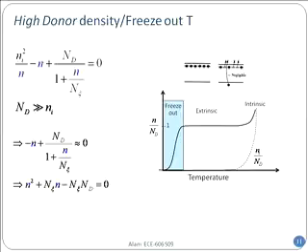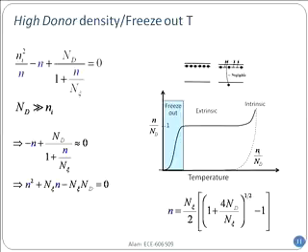And once you solve for it, you'll get an expression like this, which goes with N sub xi and the number of donor density. Now, don't worry about these things, right? This is so simple. Don't even have to think about it. Now, after you have calculated N, however, from this expression, you should put it back in the original expression with Ni squared divided by N to check whether the P, the number of holes, is indeed small or not.